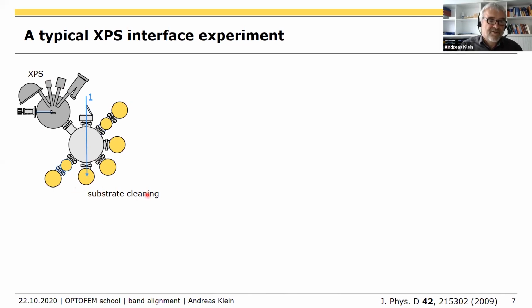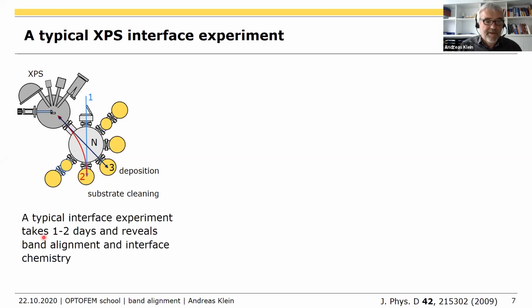So the surface preparation, the surface cleaning, is the first step. Then we go to the XPS and do the analysis. After this, we go to our chamber and do a deposition. Then we go back to the XPS and do the analysis. We do another deposition, go back to the analysis and so on. After a certain number of deposition steps, the experiment is completed. Such a typical experiment may take 1 to 2 days, depending a little on the deposition temperature. And we can identify the band alignment and the interface chemistry.